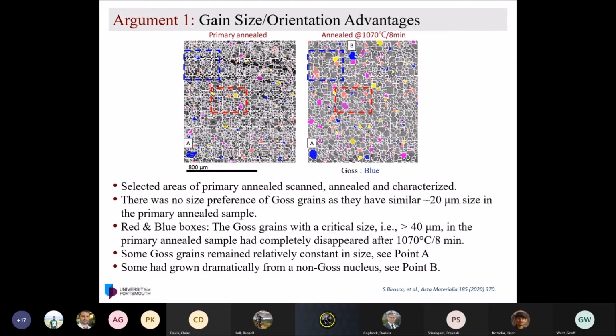When you look at the blue box and the red box here, in fact, we found these Goss grains have a critical size of over 40 micrometers. And when you look at it after annealing, they disappeared. That was out of our expectation. So the grain size advantage doesn't mean much in that early stage of grain growth.